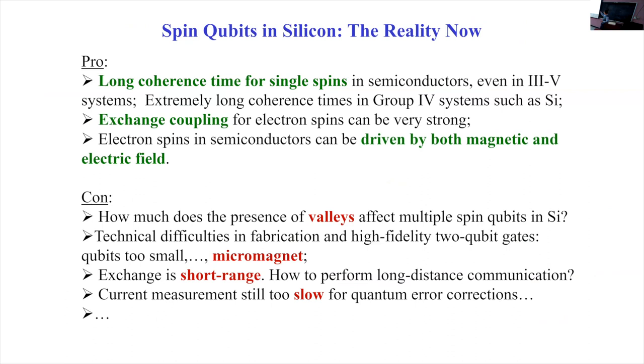Again, we have very long coherence time. Even in gallium arsenide, after 2005, people pushed along that direction a bit further and showed that even there you can implement strategies to enhance the coherence time to overcome the effect of the nuclear spins. But in silicon, especially with isotopic purification or enrichment, you can have really good coherence time. Okay. Exchange coupling is very strong, and the spin rotations can be done both magnetically and electrically. Okay. But we still have issues to deal with. Even with those high fidelity gates, as you can see from those papers, they're all implemented in double quantum dots, just two qubits.